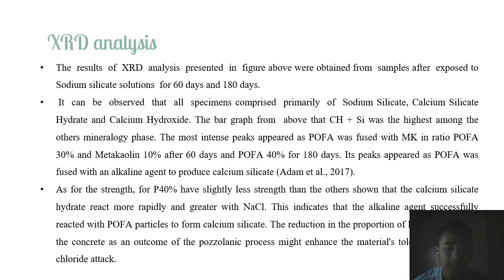As for the strength, 40% of POFA has slightly less strength than the others, showing that the calcium silicate hydrate reacts more rapidly and greater with sodium chloride. This indicates that the alkaline agent successfully reacted with POFA particles to form calcium silicate. The reduction in the proportion of lime accessible in concrete as an outcome of the pozzolanic process might enhance the material tolerance to sodium chloride attack.